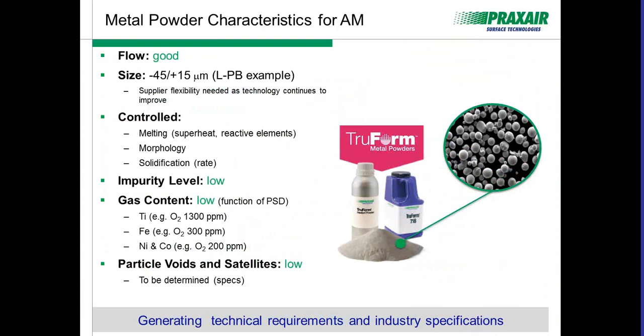We really specialize in that. If we pour the metal hotter, we can maintain more spherical powders. If we control the recirculation of fine powders, we can prevent certain satellite fractions from rising up. And in doing so, we can really create great flowability. And that's what we're looking for in additive manufacturing.